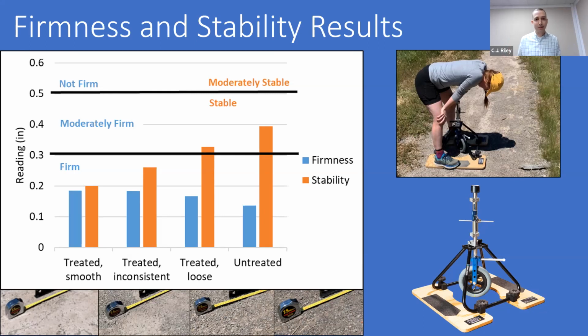And even with that, it's still considered stable. So the fine aggregate that was there really was sufficient to provide enough stability when it was integrated with the soil. And we had a reasonably good trail to begin with. But as the prior research has shown, and this really backs up, when we add this ash cement mixture, we do improve the stability effectively by binding that surface material. And so you can see that orange bar falling below, or really farther down the y-axis.